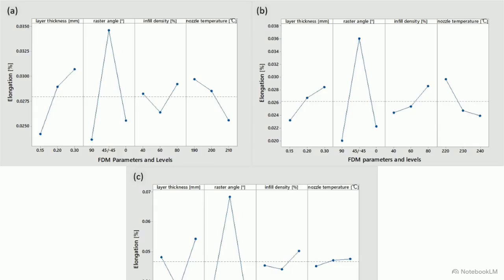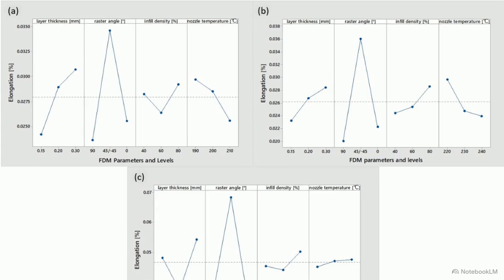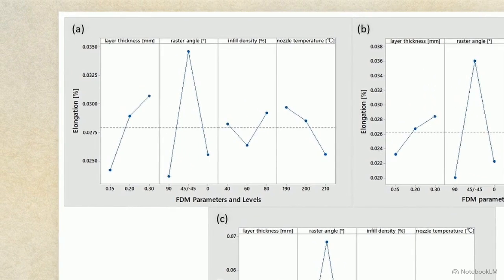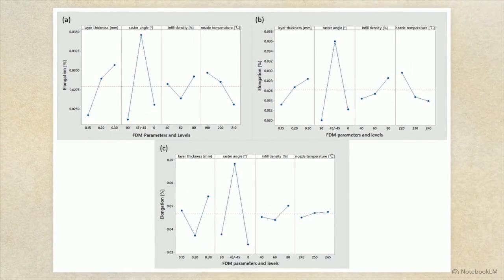These main effect plots track how the exact same printing parameters influence elongation. The response is completely inverted. The 90-degree raster angle that maximized rigidity now yields the lowest possible ductility. The optimal parameter for elongation shifts to an alternating 45 and negative 45-degree raster angle. Applying this alternating angle improves ductility by 47% for PLA, 80.5% for ABS, and an astonishing 104% for CPE. This data points directly to the internal structure of the print.